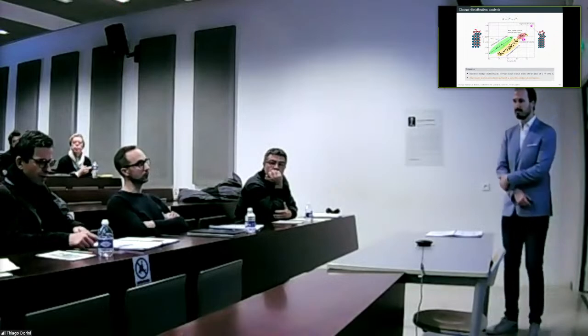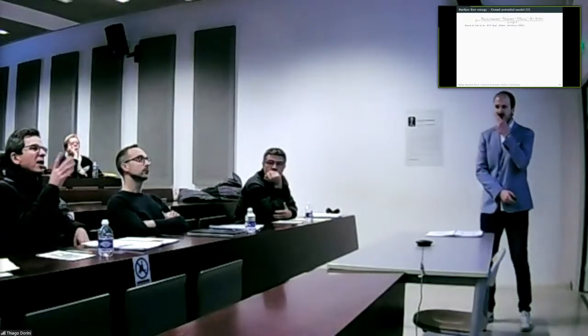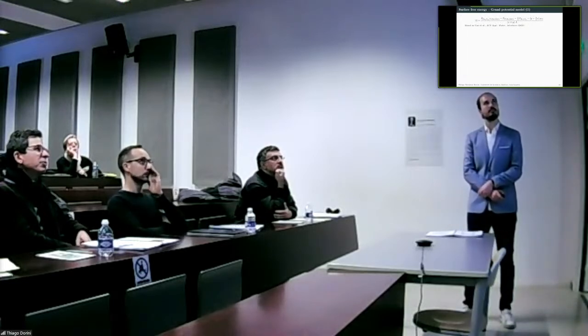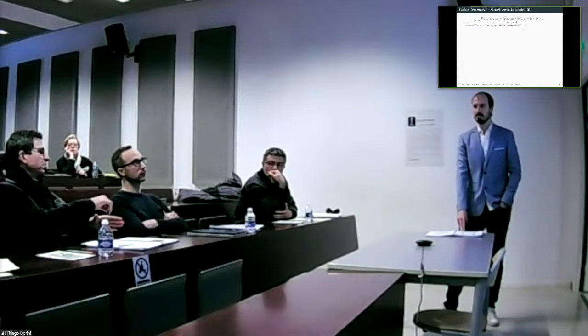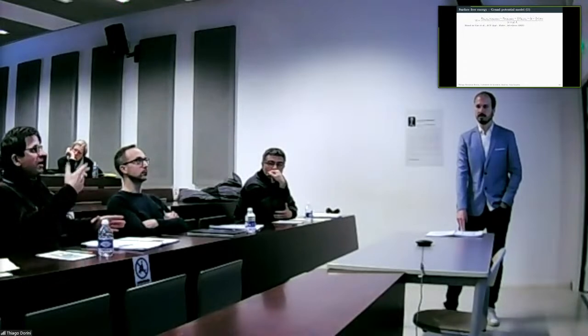Okay. For the titanium-based oxides, here I would like to have a look at the formula on slide 41, this grand potential formula. I'm not sure if I understand it correctly, but you need to divide this energy difference by the number of atoms and by the area. So if you make a Gedanken experiment, you take a 1-by-1 cell with your oxide, and it happens that it has just one atom. And then you do exactly the same calculation in the 2-by-1 cell. You would expect to find exactly the same energy. It is exactly the same structure. But you have two atoms, and the area is twice larger. So you divide by 2 and by 2. You will not find the same thing. That'll be a factor too many.